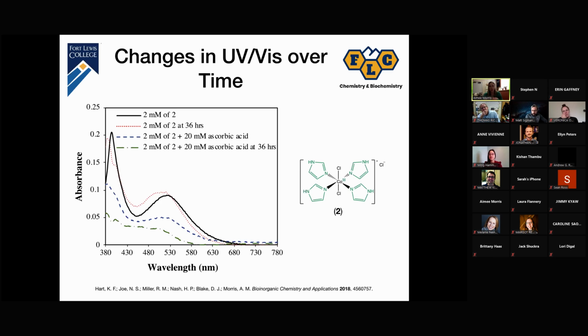And so, because it's a hotly debated idea, I still wanted to investigate, can this cobalt complex become reduced under biological conditions? Whether or not that turns out to be the mechanism, if this has potential as a prodrug, it's something that we needed to look at. And so what we did is we took this cobalt(III) complex and we introduced a biological reductant. We introduced ascorbic acid, and we did in fact see evidence by UV-vis that this can become reduced to cobalt(II) in the presence of a potential biological reductant. And so again, whether or not this becomes reduced, still hotly debated in terms of ruthenium systems, and cobalt systems may turn out to be completely different, but it's also something that's super interesting.